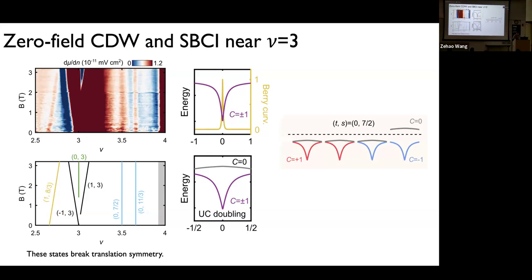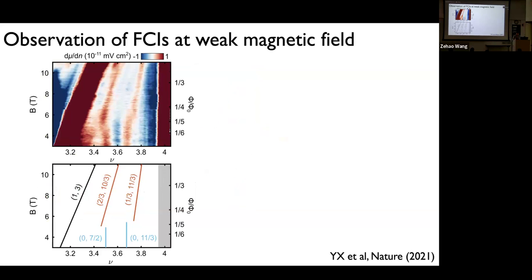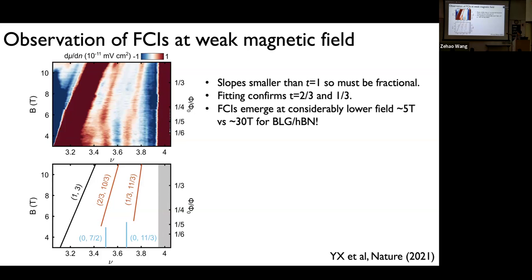But the point here is that at low magnetic field, we see states that break translation symmetry, and depending on how you fold the bands, you will get different states. The more exciting thing is that when you increase the magnetic field, you see that these vertical states abruptly disappear, and instead they are replaced around 5 Tesla by states that have slope. And you can actually compare already the slope with the very broad red feature there, which is an integer state.